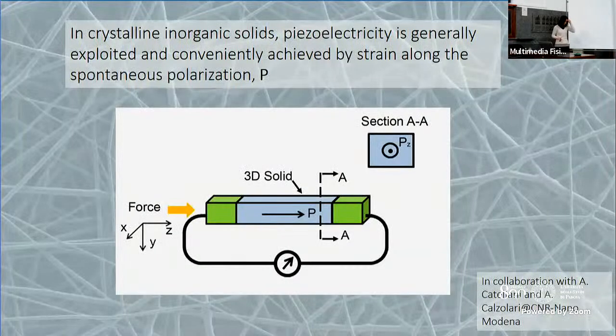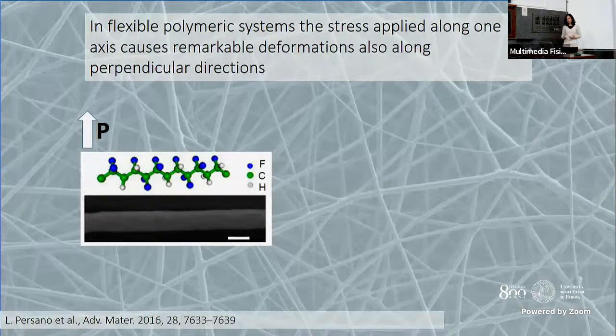However, most of the theory so far available is based on crystalline materials. So if we consider an inorganic 3D solid, piezoelectricity in this material is generally exploited and conventionally achieved by applying a force in the direction of the spontaneous polarization vector of the material, and this direction is established by the crystalline shape of the material. This is not the case of flexible polymers, because in these materials, when you apply a stress along a certain direction, you can cause remarkable deformations also in the perpendicular direction.